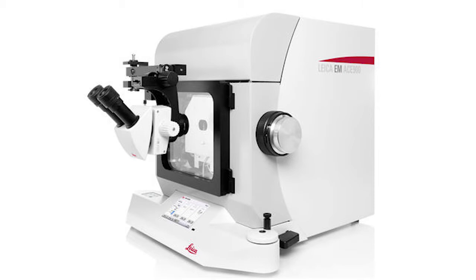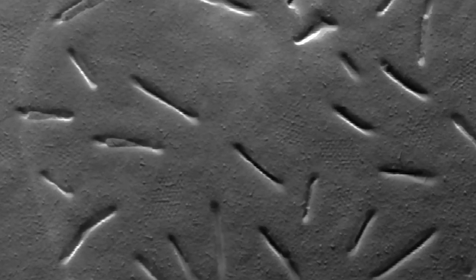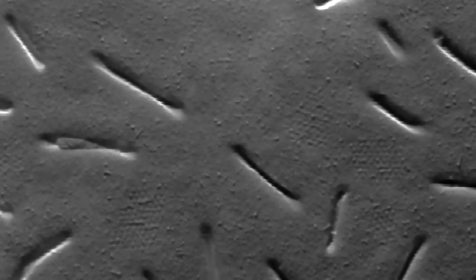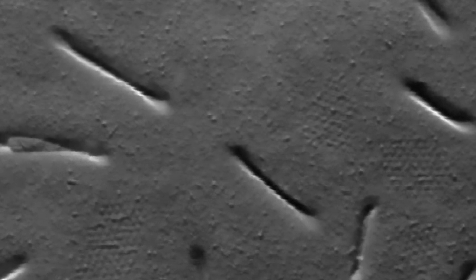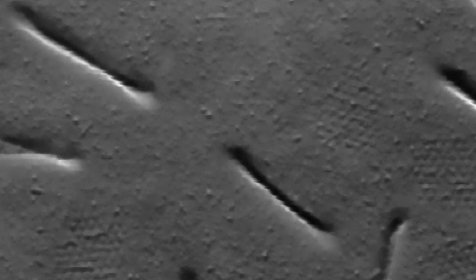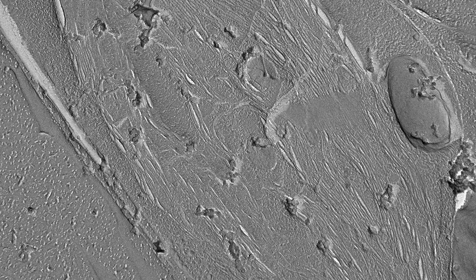The Leica ACE 900 operates at high vacuum and is equipped with 2 e-beam sources for platinum and carbon coating replicas. The ACE 900 has several different holders to accommodate a wide range of samples and can generate double replicas as well as knife fractured replicas. Freeze fracture is suitable for examining both biological as well as soft materials and polymers.